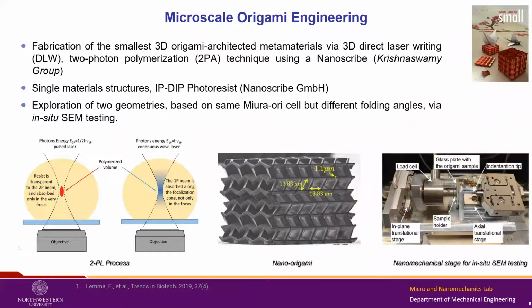So how did we do this? As I said, the first challenge was the challenge of folding, and to do that, we went to the micro and nanoscale. We fabricated via 2-photon polymerization, 2-photon lithography, which was done by Sridhar Krishnaswamy's group here at Northwestern. They have a lot of experience printing these kinds of structures, which are quite complex actually, because you have angles and panels, and you have a big difference between the thickness of the panels and the actual length of the unit cells.